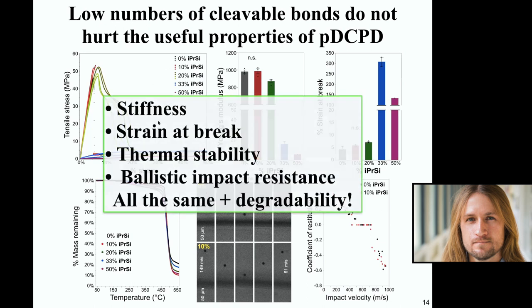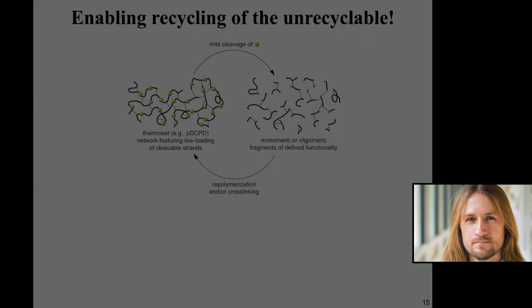For example, the stiffness, the strain at which it breaks, so how far you can stretch it before it breaks, its thermal stability, its ballistic impact resistance, which we were able to measure in collaboration with Professor Keith Nelson in the Department of Chemistry at MIT. All of these features, if you compare the non-degradable version to the degradable version we made, they're all the same. But now we have added this very selective ability to degrade the material. So what can we do with that?